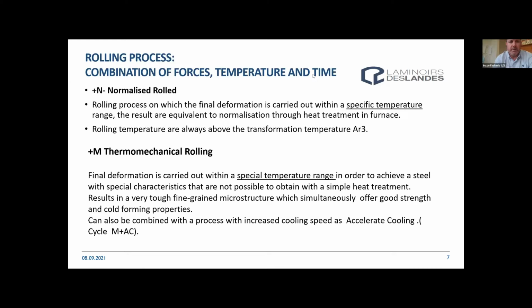And we also have the objective to produce plus M, which is called thermomechanical rolling. That means that the final deformation is carried out within a special temperature range in order to achieve a steel with special characteristics that are not possible to obtain with a simple heat treatment. The result is very high quality steel, with a fine grain microstructure that simultaneously offers good strength and cold forming properties. This can also be combined with increased cooling speed, as in the accelerated cooling process.